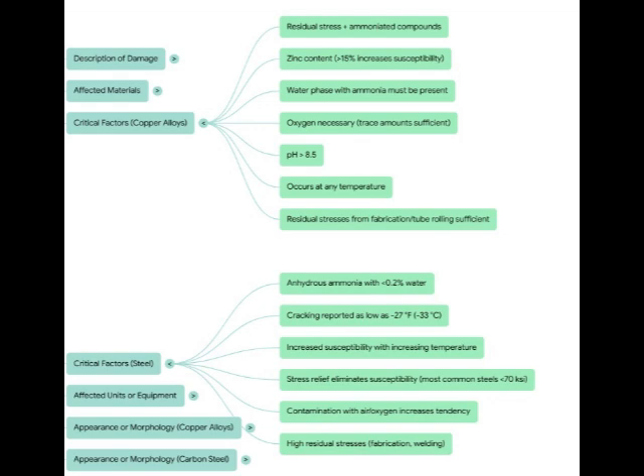First, you need that water phase, obviously, with the ammonia dissolved in it. Second, the environment has to be alkaline. We're talking pH above 8.5. Alkaline, right. And third, this is critical, you need oxygen. Now, it's an aqueous alkaline environment, but you still need some oxygen. Even trace amounts, the source says, are enough to get that corrosion reaction going that leads to the crack.